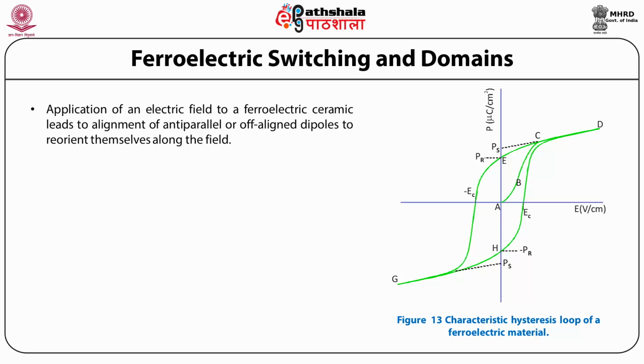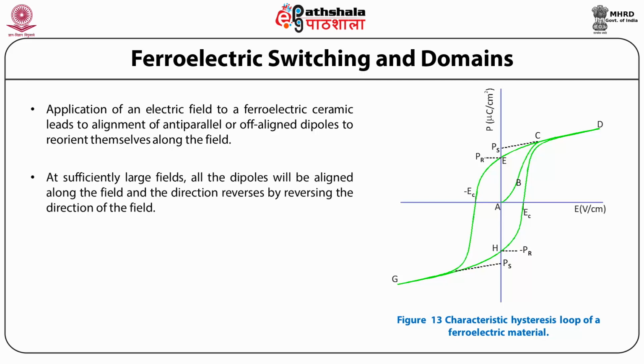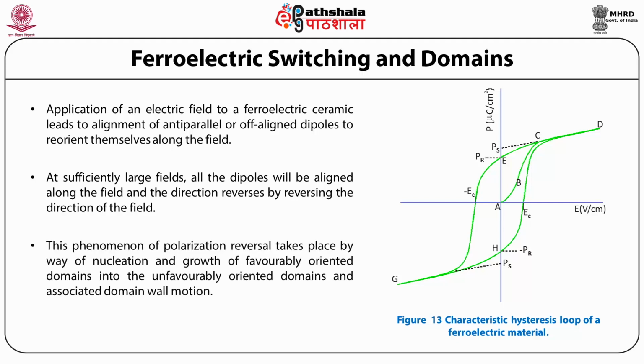Application of an electric field to a ferroelectric ceramic leads to anti-parallel or off-aligned dipoles reorienting themselves along the field. At sufficiently large fields, all the dipoles will be aligned along the field, and the direction reverses by reversing the direction of the field. This phenomenon of polarization reversal takes place by way of nucleation and growth of favorably oriented domains into the unfavorably oriented domains and associated domain wall motion.